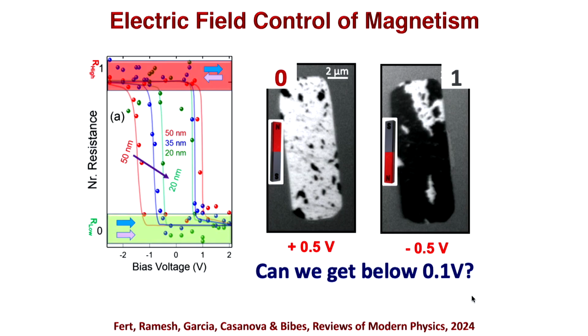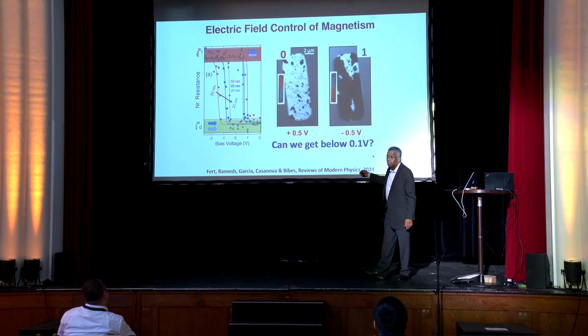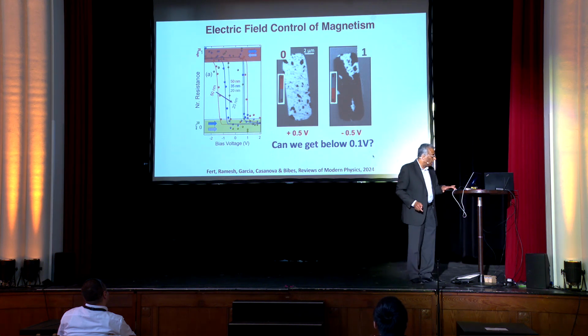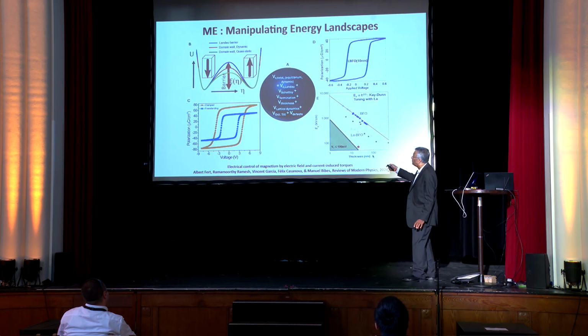So we know that you can control magnetism with an electric field. You can put a spin valve on top of this, and you can actually measure that and prove that you can switch magnetism at 500 millivolts with an electric field. These are photoemission-based or XMCD-based measurements. Can we get below 100 millivolts? It's a challenge. Okay, the challenges are captured on this slide.